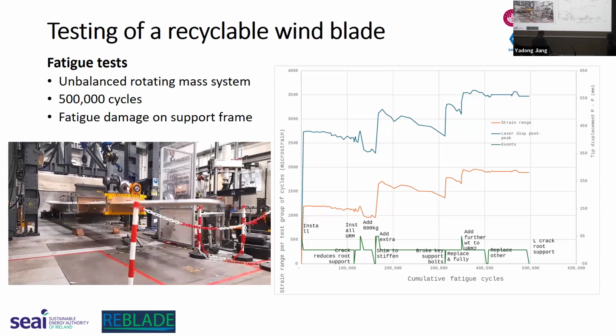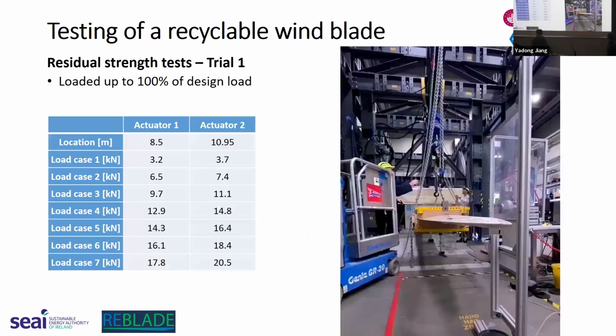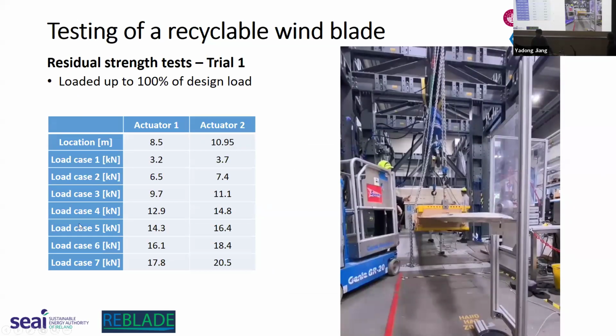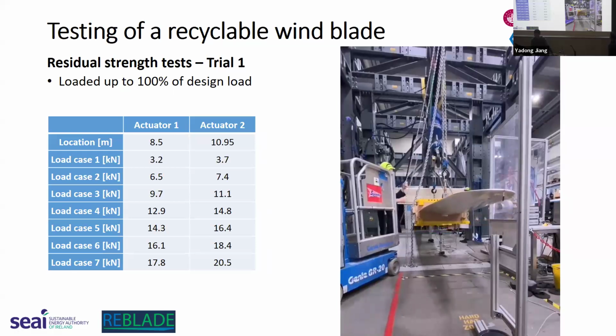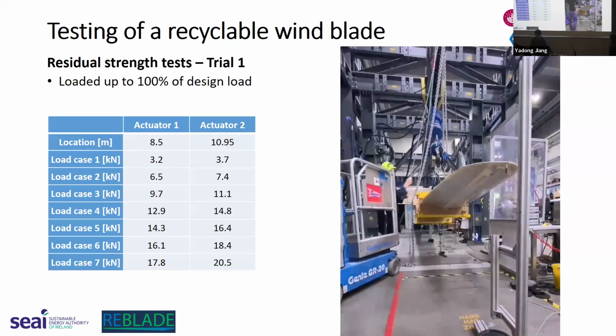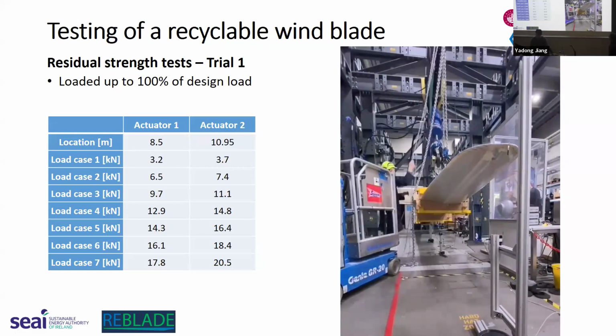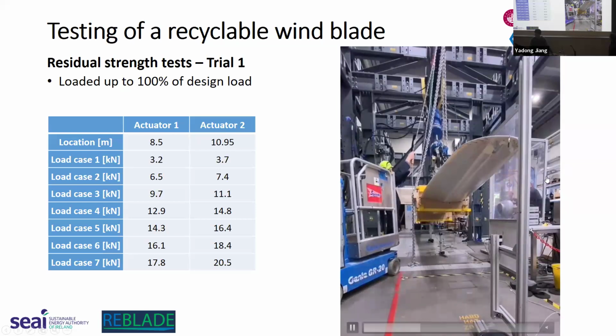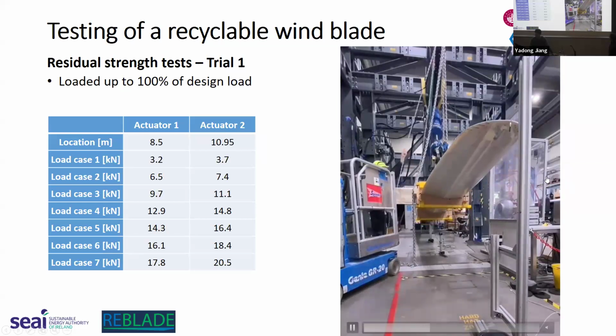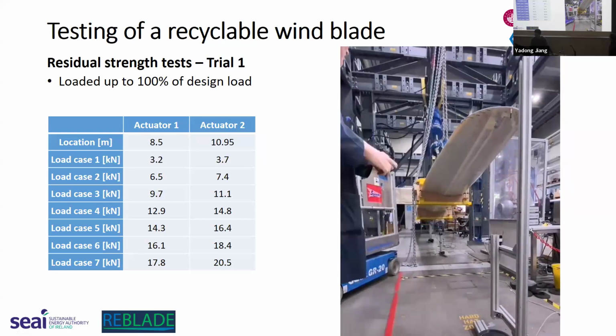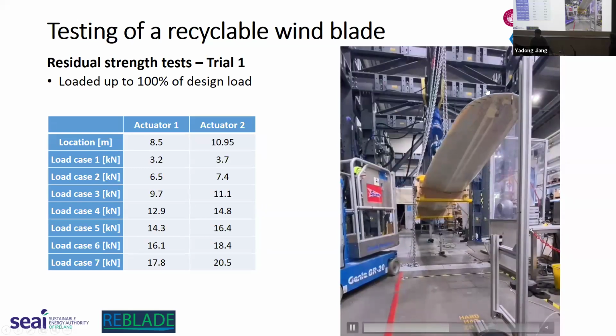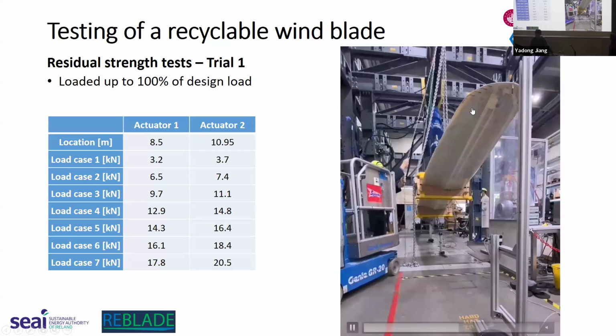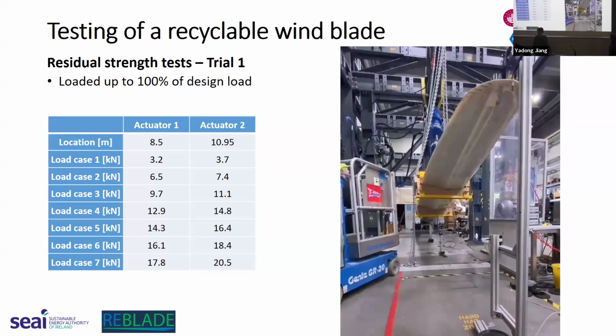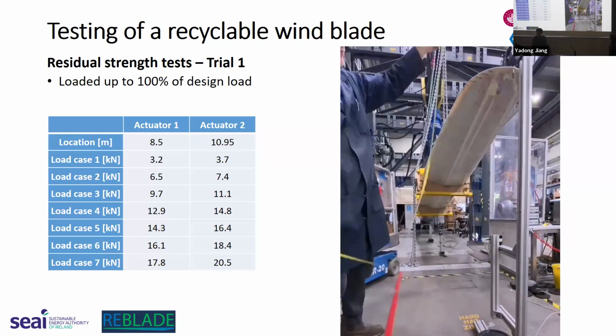And then we repeated the static test. And in this case, we tried to load it in the first trial, up to 100% of design loads in 7 load cases. And here is a sped-up video of this testing, and you can see there is quite a lot of deflection at the tip of the blade, but we didn't observe any failure of the blade, which is a good thing.